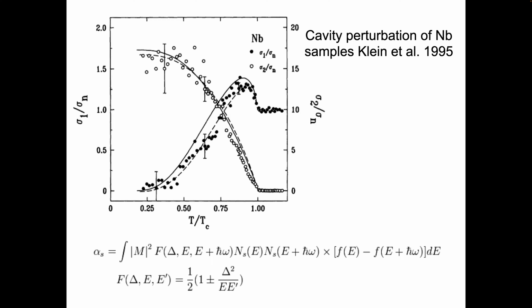It's a superconductor, but this is a peak in the dissipative part. So that's a kind of a strange state of affairs. You go into the superconducting state and the dissipation goes up, right? Which is not what you would expect. It's a superconductor. And so that's kind of a non-trivial prediction of the BCS wave function, that when you enter into the superconducting state, the dissipation first increases and then decreases. This was first seen in spin relaxation rates in nuclear magnetic resonance. There are other versions of it. This is it in the microwave cavity experiment.